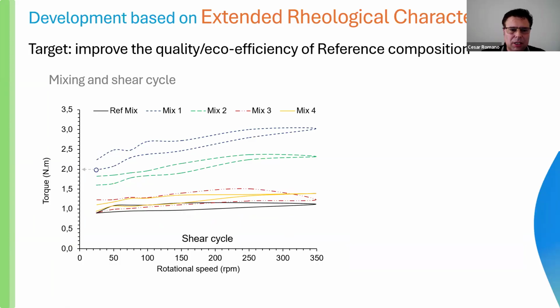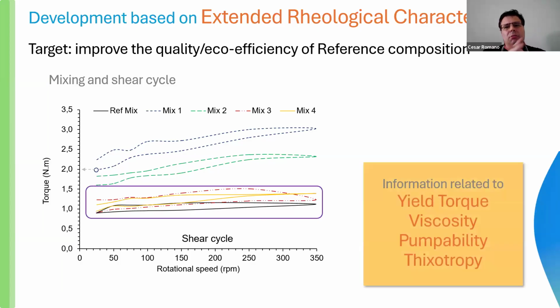For sure, we had also differences in the yield torque. This first point of yield torque is correlated with yield stress, and this can be correlated with viscosity. And it's possible to see that 2 of these 5 compositions are different from the others, and these mixes 3 and 4 presented the same pattern of the same rheological profile or the same level of torque observed for the reference material. So we had information related to the yield torque, to the viscosity, to pumpability, to thixotropy of the material. That is very important when the material is deposited in the layer.